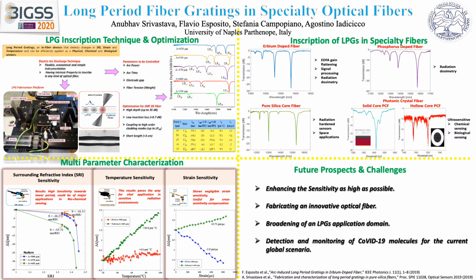So we optimized for standard SMF-28 fiber. We can see here that for different grating periods, we achieved around 35 decibel, and we achieved low insertion loss of less than 0.7 decibel, and also coupled to higher order cladding modes up to LP08 as we approach the lower order period. And also the most important is we achieved a shorter length of the grating, around or less than 3 centimeters.